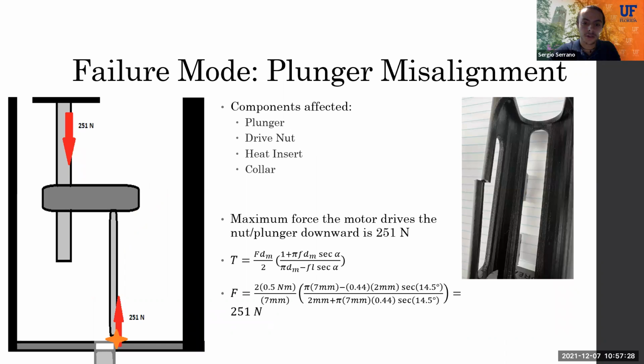With our design, under normal operation, the plunger does not need to completely exit the chamber. However, it is possible for the drive nut to be moved up higher such that the plunger comes out. In the case that there's a misalignment between the plunger and the chamber hole during reinsertion, an interference between components could lead to failure.